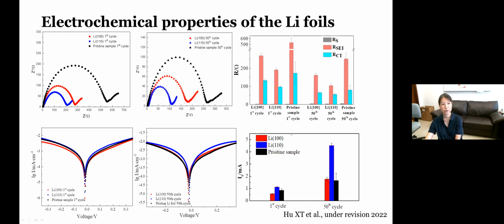Right, and further electrochemical calculations, including EIS and Tafel test results, are shown here. We have 3 samples compared, and those are cycled at the first cycle and the end of the 50 cycles. For the 3 samples, we see very similar results in terms of the resistance of the bulk, right? And this makes sense because we don't expect the different surface texturing would affect the conductivity of the metal foil at all. But then in terms of the SEI resistance and the charge transfer resistance, there's quite a bit of difference. But all 3 samples have a similar trend.